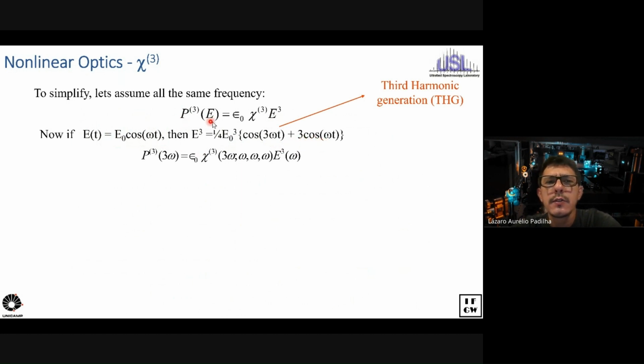In other words, the polarization that you create will have a term that oscillates with 3 omega and a term that oscillates with omega. The term that oscillates with 3 omega is called third harmonic generation. So you're going to create a polarization that will oscillate with 3 times the energy of the driving field, which means that you're going to have a generation of what we call third harmonic. So the polarization will be written like this.